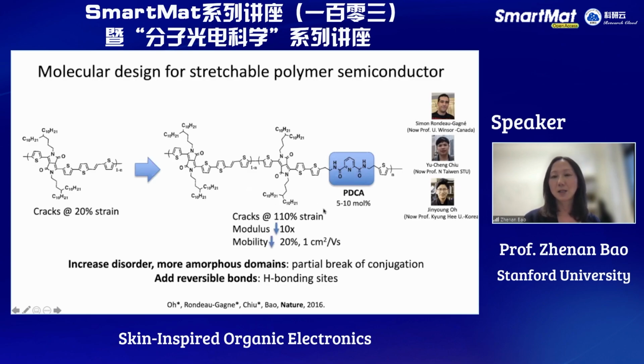So one of the successful concepts that we reported a while ago was to think about how we can increase disorder, but at the same time not compromise the charge transport too much. There's always some compromising, but the key is to get both in the optimized condition. To do that, we explored a conjugation breaking mechanism to introduce some non-conjugated unit into the originally very rigid conjugated polymer, and that increases the disorder.